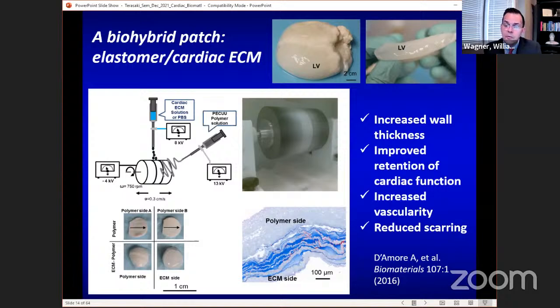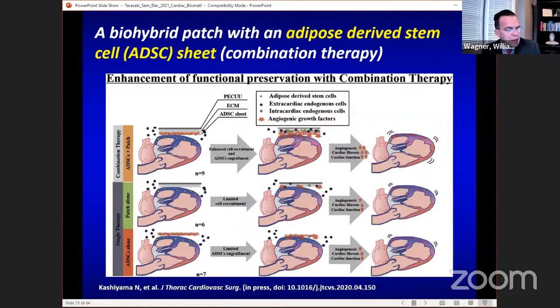So similar to the patch data I showed you before, but we are doing electrospinning now instead of thermally induced phase separation. So a more recent take on that is I had a visitor from Japan in my group, Dr. Kashiyama, and he had worked with a number of the Japanese groups that make cell sheets. And so we made an adipose derived stem cell sheet. And that has actually been used clinically. They've applied that to infarcts. And we wanted to know what would happen if we took the stem cell sheet and put it below our open face sandwich. So theoretically, having the ECM on top of the cells, on top of the infarct, seemed like a really nice combination. And then the polymer giving mechanical benefit.